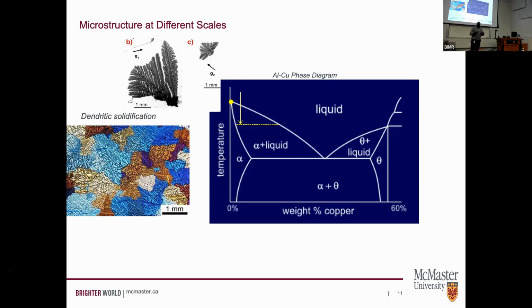So if I happen to find myself in a temperature and a composition where I happen to be able to support two phases, I tend to form these nice dendritic-like patterns that we call in materials. In the high temperature liquid, you get these nuclei, they grow, and then they coalesce, and they form these sorts of nice microstructure patterns where each of those are different grain orientations.